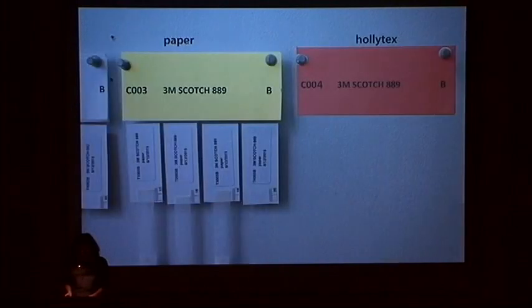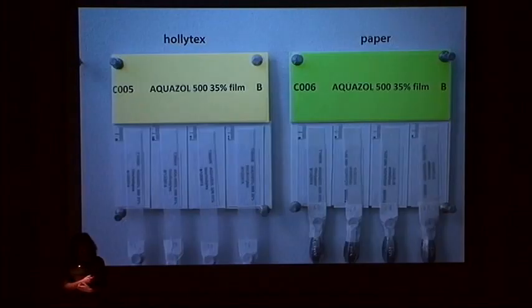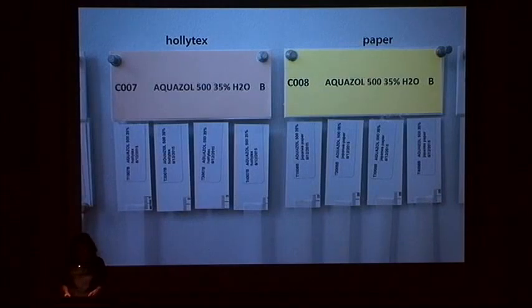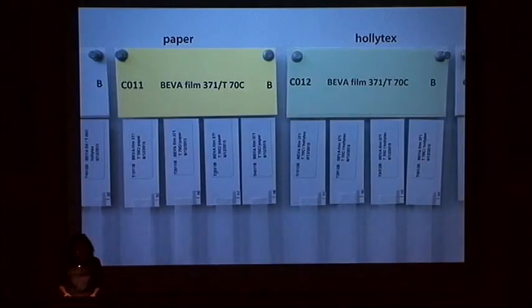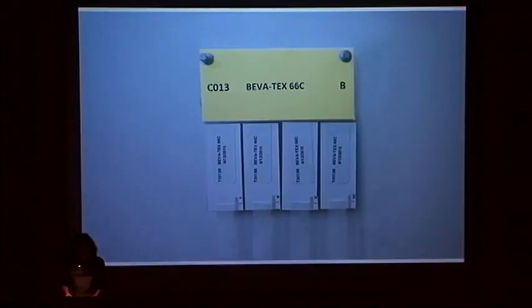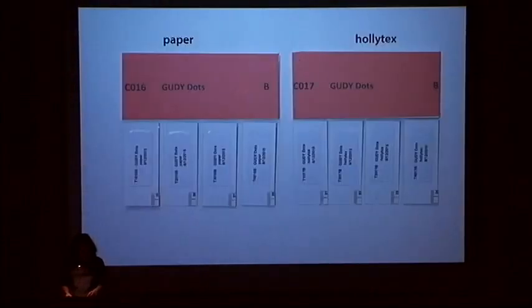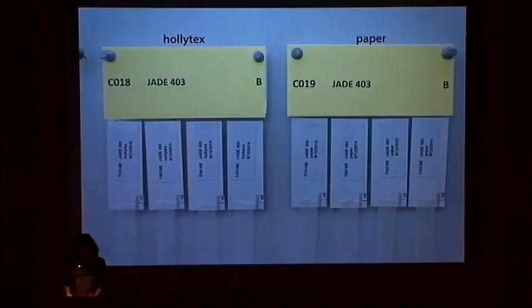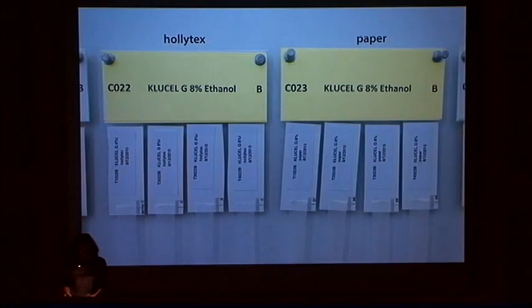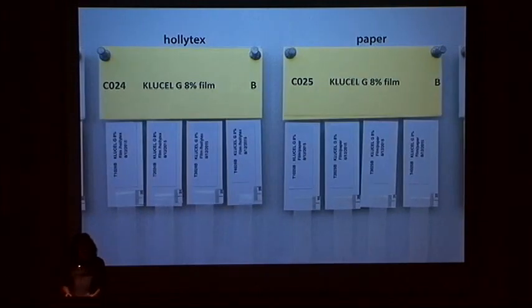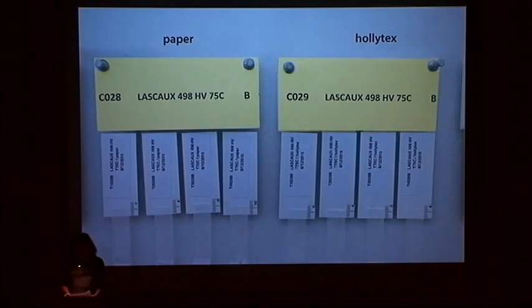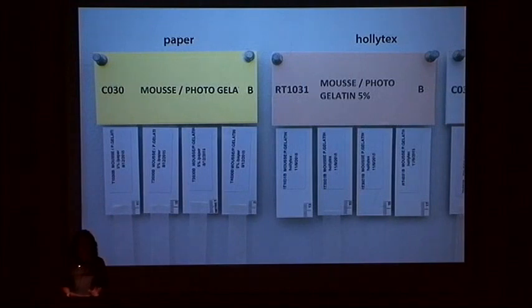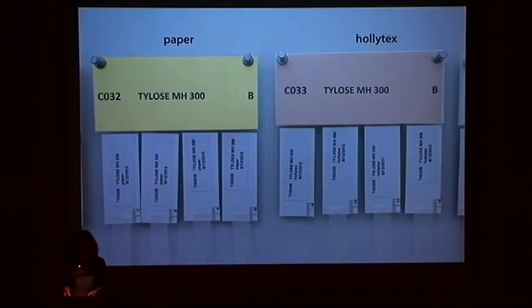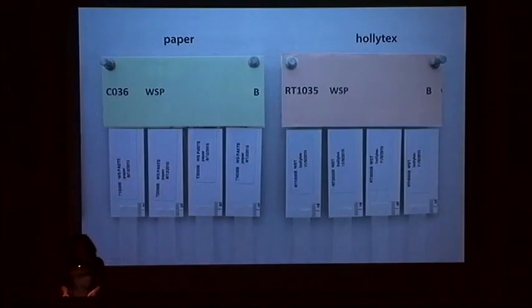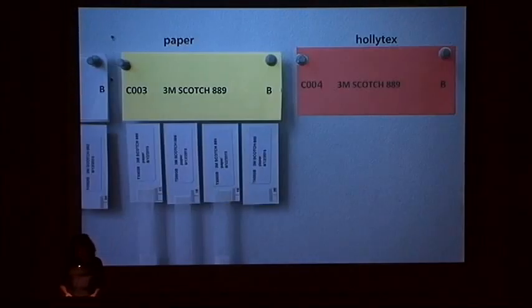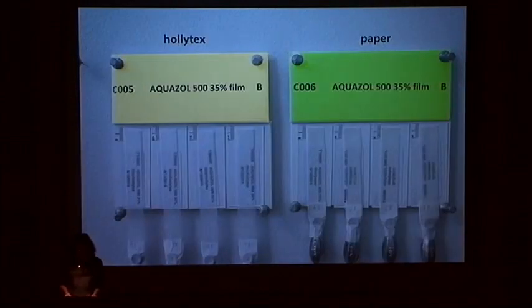In this video, we are going to scroll through the status of the peel test as of last week. This is after only 4 of the 9 months of the experiment. The board contains again 4 samples with identical carrier, Japanese paper or Hollytex, and of course for tapes, this does not always apply. Red colorized fields are outright failures, yellow are borderline or questionable systems, and light green are so far looking good, but the brightest green are so far the ones that didn't show any creep at all. Instances where two different colors appear simultaneously are instances where the carrier is having some influence on the bond strength.